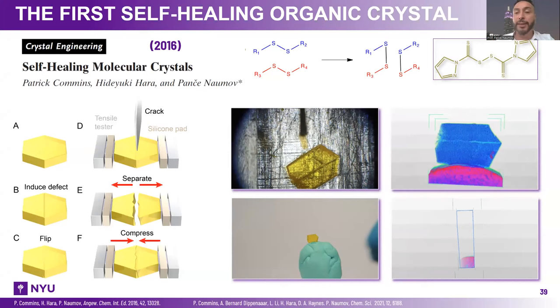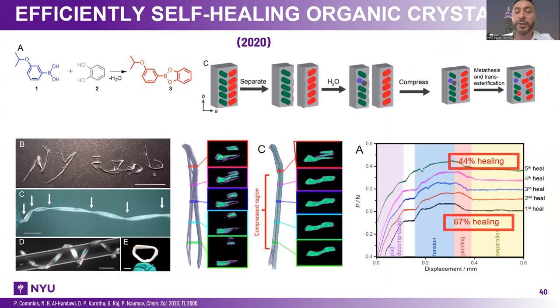So a lot of eyebrows were raised, you know, people were asking, is it true or not? Yes, it is. Two years later, we actually improved this by an order of magnitude. So this is a completely different chemistry. It's a boronate metathesis between resorcinol and boronic acid. And now we have healing of 67% in the first round, going down to 44% in the fifth round. So of course, there is some decrease in efficiency due to imperfect coupling between the two parts or, you know, debris falling between the crystals and so forth. But in principle, this works. So this was taken by other groups and they published very nice papers by using different chemistry to demonstrate self-healing.